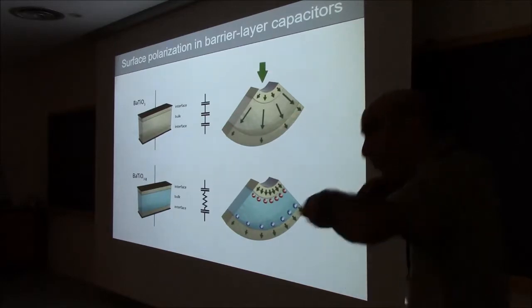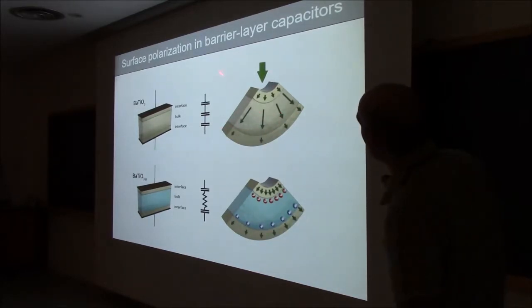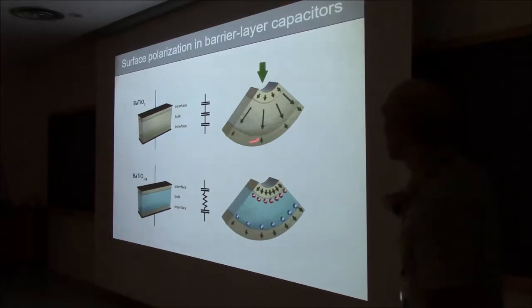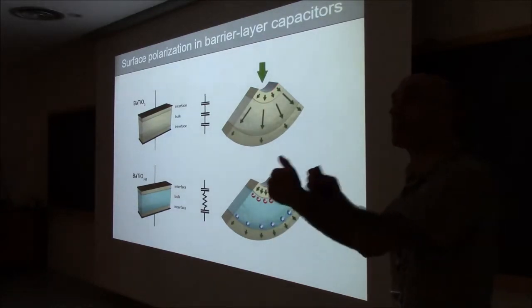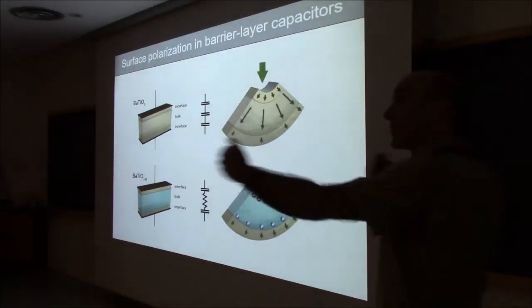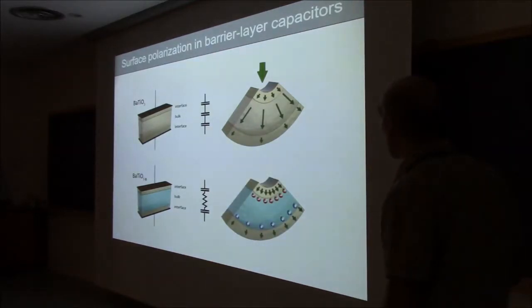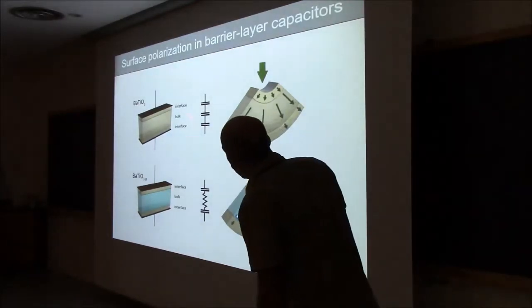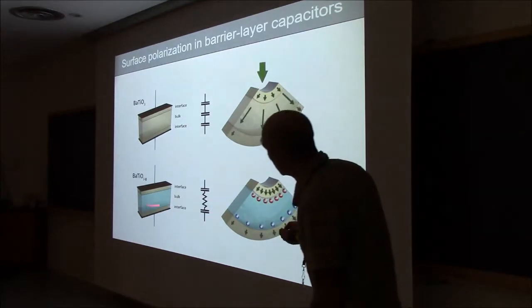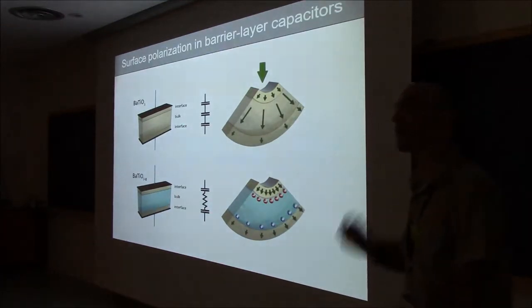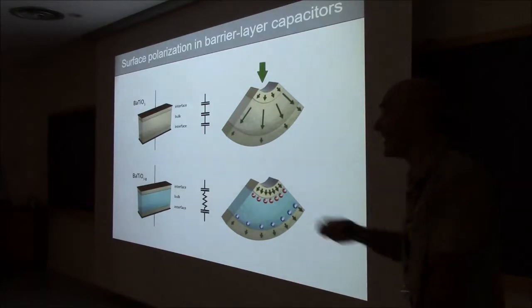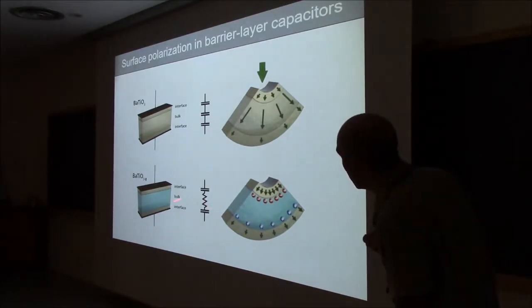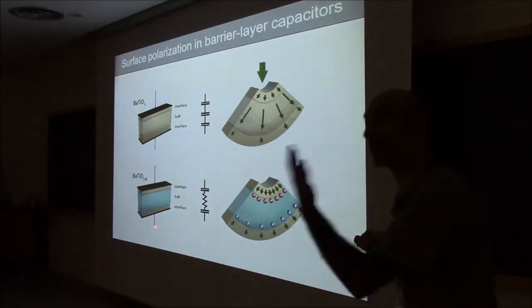And likewise, when you try to bend it, you get the bulk flexoelectricity, you have a surface piezoelectricity, and these 3 things, because there's 3 elements, more or less will try to match each other because we want to have a constant displacement vector. Right. If I now take the bulk away, I turn it into basically something metallic, something conducting, something that gives me as much free charge as I need, then it's as if this no longer existed. Okay, this dielectric element no longer exists because it's conducting.